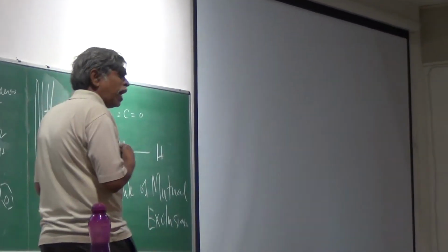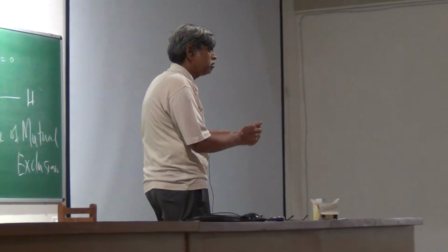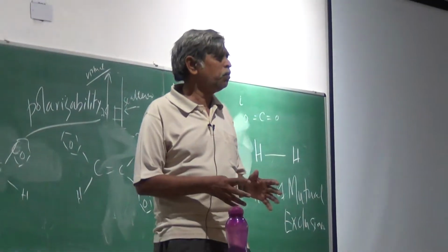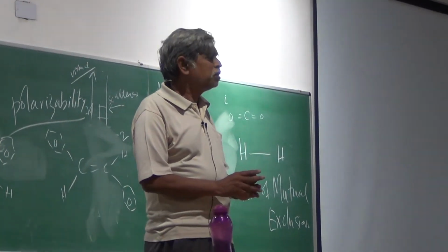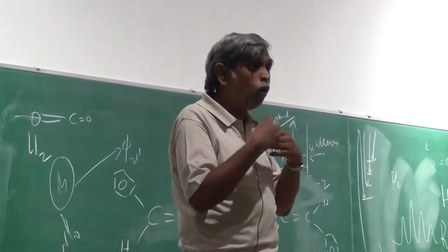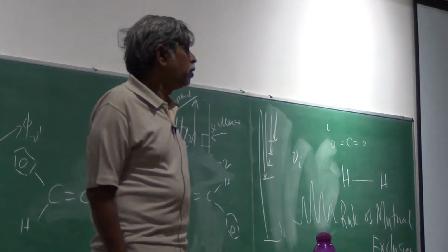And therefore you see Raman without contamination from the absorption emission process. So what have you done? You have actually lowered the efficiency of your scattering process, but you have discriminated extremely strongly against the fluorescence. Smartly using 400 for scattering is very bad, simply because you have an emission going on, a fluorescence experiment going on, much against your own desires. So what you have to do is to use a wavelength that is not appropriate for an absorption process. So use 700 nanometers and you will find you have lost out on scattering, but you have gained on this differential process. You have completely suppressed fluorescence, and all you're going to be seeing is only the Raman process.